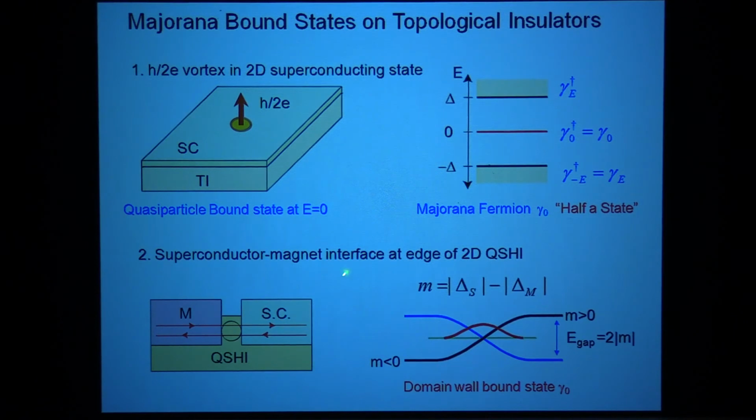There's a difference, though, which is that in the one-dimensional topological superconductor, you actually have to break time reversal symmetry in order to get the Majorana mode, and the superconductor itself breaks time reversal. Here, the superconducting state doesn't break time reversal, but it's the insulator on the outside that does break time reversal. And so this is sort of a complementary situation to the one-dimensional topological superconductor.